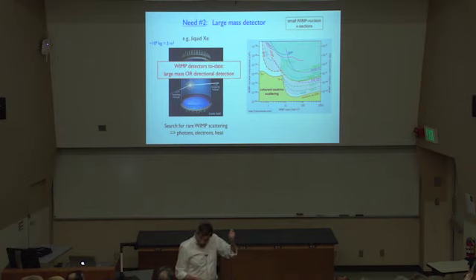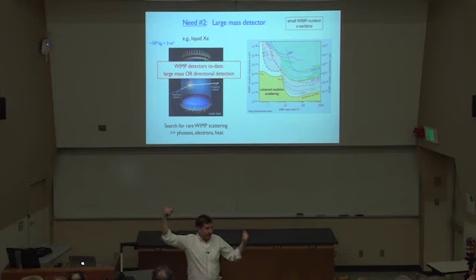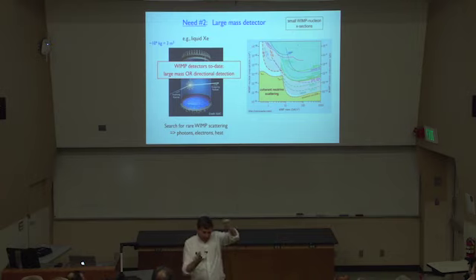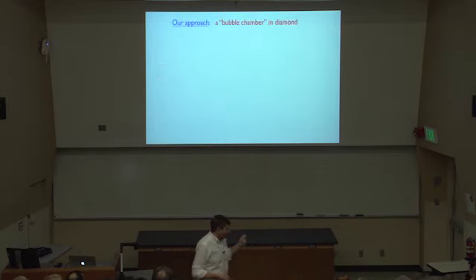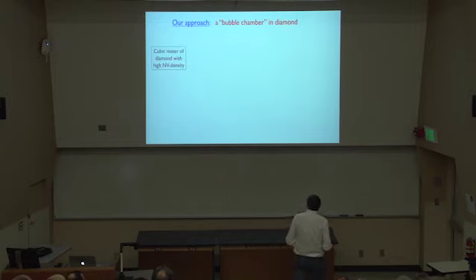To date, there have been people doing directional detection with gas-based detectors. They don't have large mass, and are not scalable to large mass. Or, of course, with liquid xenon and other things, large mass, but it's a liquid and no directional detection. When there's a detection in liquid xenon, if there is, or there would be with neutrinos, you get a flash of scintillation light. You can see an event occurred, but there's no scar, no indication of which way the WIMP or neutrino came in. So our idea is to make something like a bubble chamber that can leave tracks in diamond.